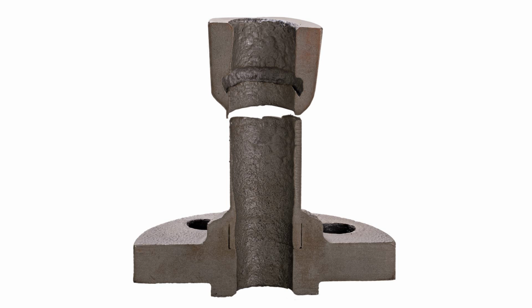Two types of sulfate-induced hot corrosion are generally distinguished. Type I takes place above the melting point of sodium sulfate and type II occurs below the melting point of sodium sulfate, but in the presence of small amounts of SO3. In type I, the protective oxide scale is dissolved by the molten salt. Sulfur is released from the salt and diffuses into the metal substrate, forming discrete gray/blue-colored aluminum or chromium sulfides, so that after the salt layer has been removed, the steel cannot rebuild a new protective oxide layer.